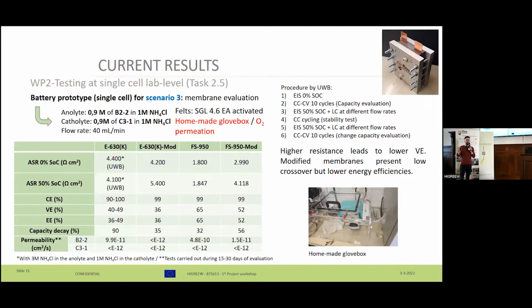So since the HIGREEW guidelines are interested in the scenario 3, we wanted to perform some membrane evaluation according to the procedure suggested by the University of West Bohemia by cycling the battery, and at a given electrolyte configuration at 900 millimolar of the active species in 1 molar of, in this case, ammonium chloride, we evaluated the resistivity of our membranes, pristine and modified ones. Well, I have to remark that in our case, we were using a homemade glove box, so we have some oxygen permeation that we have to keep in mind, but to compare with our results, it's okay.